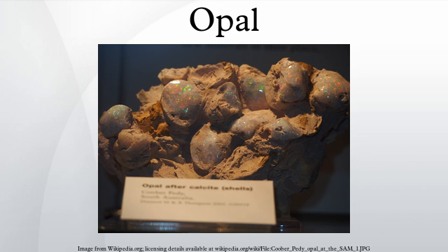Dehydration experiments and infrared spectroscopy have shown that most of the H2O in the formula of SiO2 and H2O of opals is present in the familiar form of clusters of molecular water. Isolated water molecules, and silanols, structures such as SiOH, generally form a lesser proportion of the total and can reside near the surface or in defects inside the opal.